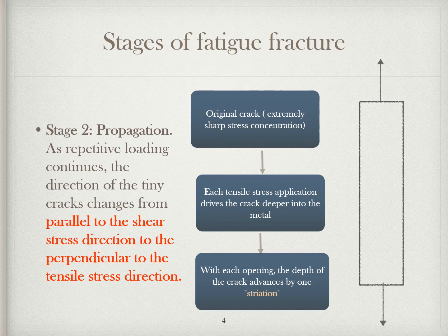Assuming that the maximum cyclic stress is of a magnitude high enough to propagate the crack, the local stress at the tip of the crack is extremely high because of the sharp notch, and with each crack opening, the depth of the crack advances by one striation under many, but not all circumstances. Striations are very tiny, closely spaced ridges that identify the tip of the crack at some time. Striations are normally visible only at high magnification with the aid of an electron microscope.